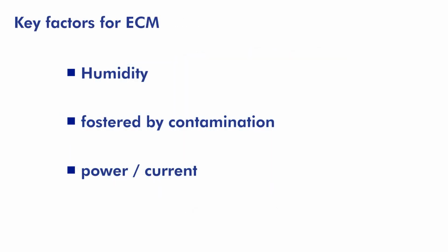Contamination is able to foster the mechanism in case of hygroscopic behavior, but it is not essential to start the mechanism. ECM results mostly in the permanent fail of assemblies by short circuits effectuated through conductive dendrites.